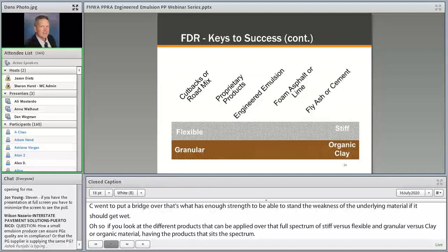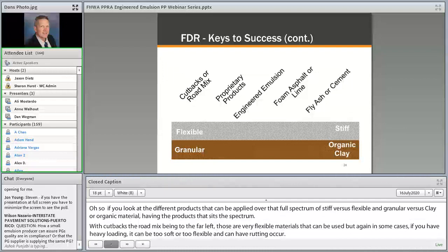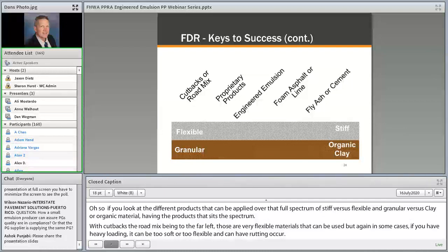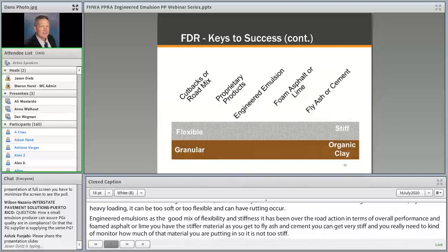Engineered emulsions is really that good balance between stiffness and flexibility, and that provides you with middle of the road action in terms of overall performance. And then foamed asphalt and lime, you're progressing more to that stiffer material. As you get to fly ash and cement, you can get very stiff, and you really need to monitor how much of that material you're putting in so you don't get it too stiff, because if you get that base too stiff, that will eventually crack up, and those cracks will reflect up through the pavement structure as well.